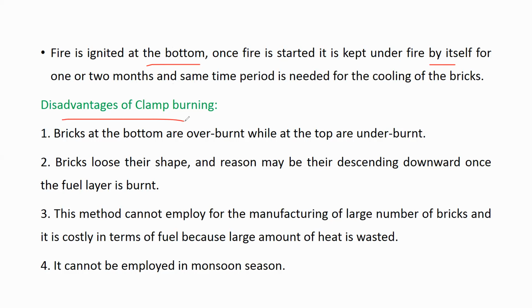Okay, there are some of the disadvantages of the clamp burning. Bricks at the bottom are overburnt. The bottommost portion of the bricks will be overburnt. Then at the topmost layer, the bricks will be underburnt. Then the middle portion of the bricks will be of good quality. Lowermost portion, overburnt bricks you will get, and at the topmost portion you will get the underburnt brick. Bricks lose their shape, and the reason may be they're descending downward once the fuel layer is burnt.